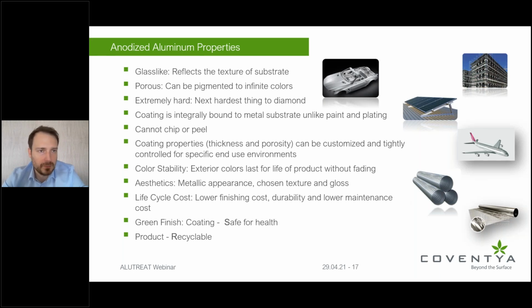You get properties like it is obviously glass-like, but because it is glass-like, you still will be able to see the underlying metal. That gives you the metallic appearance, which is very hard to find with other organic-based top coats. And because it is extremely hard, you get an enormous wear resistance that can be integrated into both functional and aesthetical look. But for me, I would say the best property, because it is a part of the material and it's not a plating, especially it's a conversion coating where we are converting the aluminum to aluminum oxide, is that it does not chip or peel or is not possible to take off from the surface by physical means. Therefore, it is a very durable coating that is on many building facades over many years that you can literally see still withstanding the atmospheric conditions.